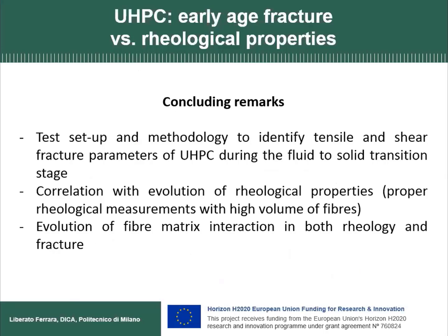So coming up to the conclusions, we have developed, designed, and validated this test setup and methodology to identify the tensile and shear fracture parameters of UHPC, basically during the fluid to solid transition stage. And we are completing this with penetration tests to identify compression strength evolution, in order to be able also to build up a Kupfer domain and its evolution over time along these early age stages of the material. We have been validating a correlation also with the evolution of the rheological properties, and also to detect an evolution of the fiber matrix interaction and its role in both rheological and fracture properties.